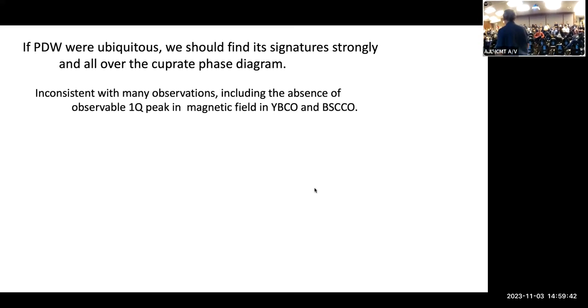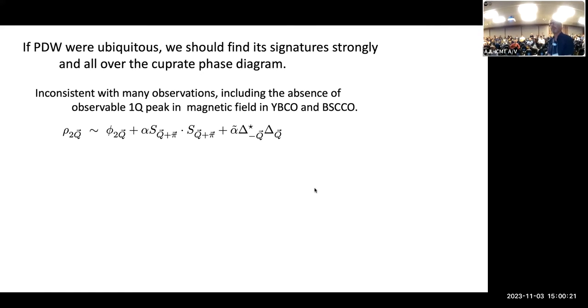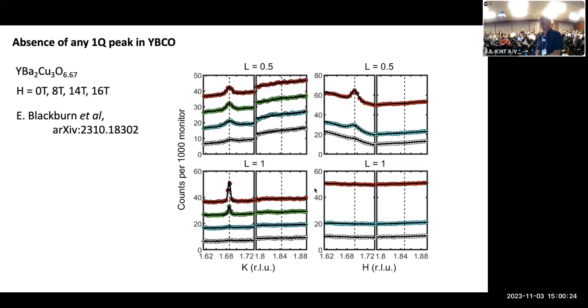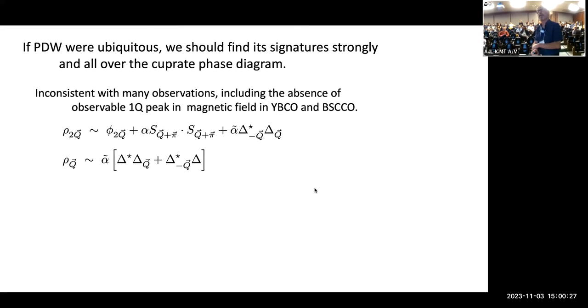But if I were to attribute it to being a signature of pair density wave, then it would be the 2Q peak that comes from the square of the pair density wave order parameter. But if I then can arrange for systems where I expect to have both pair density wave and uniform superconductivity, I should also see a 1Q peak. And this should occur, for instance, in vortex cores where the uniform superconductivity is suppressed and where pair density wave occurs. So I just remind you of this. There's the 2Q peak. Here's the 1Q peak.